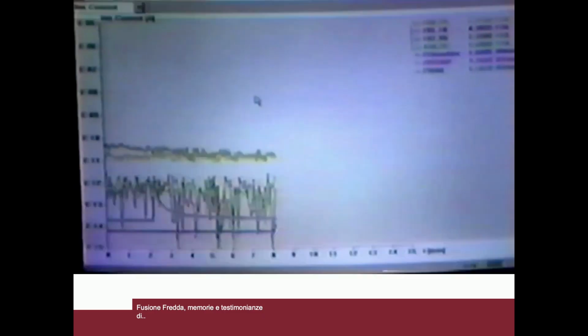This is the third computer. It's not a Macintosh; it is directly connected to the mass spectrometer with a spectrum acquisition system. As has been described, the acquisition of the signal takes place in multiple ion detection mode, in which we are able to detect the intensities of the selected ion species as a function of time. I remind you that the choice that has been made is to select, in addition to the deuterium, the valley between deuterium and helium and the neon 2+, because these are parameters that make it possible to check that the presence of helium does not derive from contamination from air.